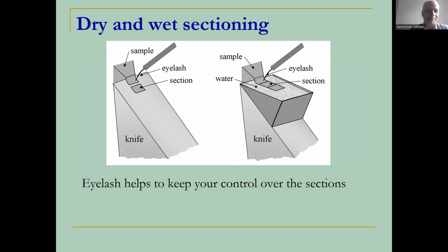And if the specimen is not reactive with water, if water does not damage the sample, then what we can do is make the sections float onto water, and this band of sections floating on the water can be picked up with the help of the grid and some tools, and we can put them into the microscope.